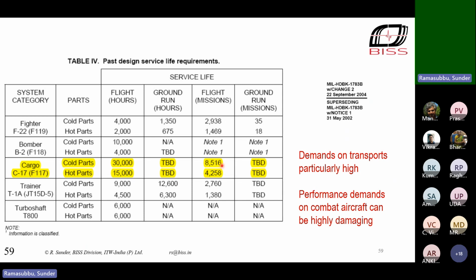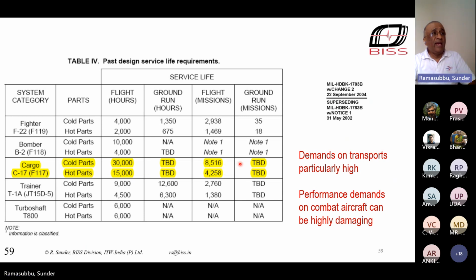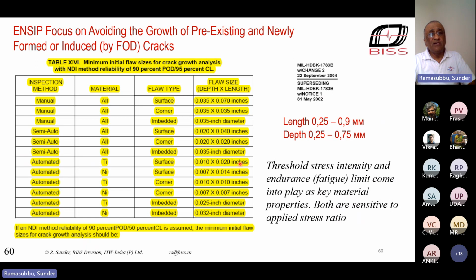So in spite of that, there are huge demands on the life of engines. You can see here for transport aircraft, it's quite huge. And at the same time, there's a huge demand on the defect sizes. In aero engines, you do not allow defects even as small as these, which means you need to have, on the one hand, non-destructive equipment which can handle the detection with almost 100% probability of detecting very small defects because they can grow rapidly. Engines are very highly stressed. Their safety factors are even less than airframes.